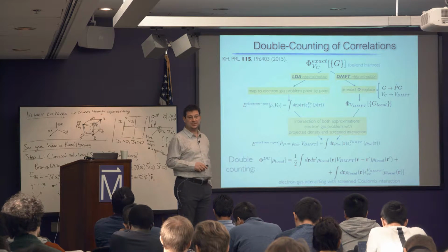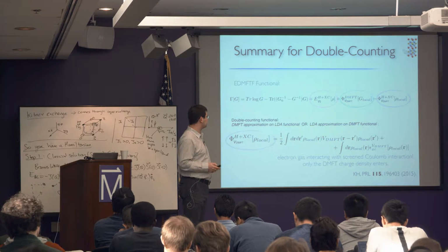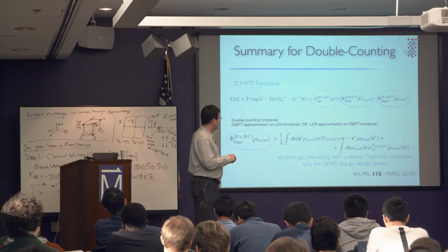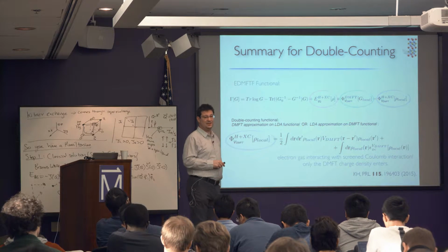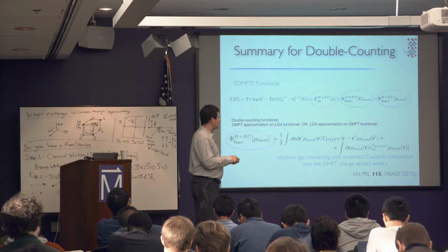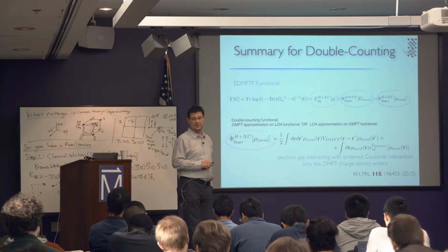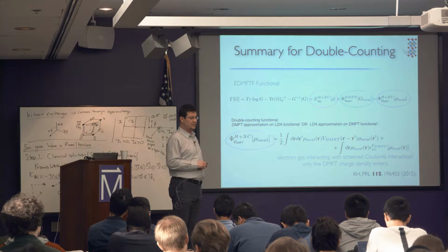And that's exactly the double counting within this approach. So the point is, we can now safely use the Kohn-Sham plus exchange correlation functional from DFT that acts on all the orbitals. Then we add the Feynman diagrams to certain more correlated orbitals, and we know how to subtract the correlations which are accounted for in both cases.